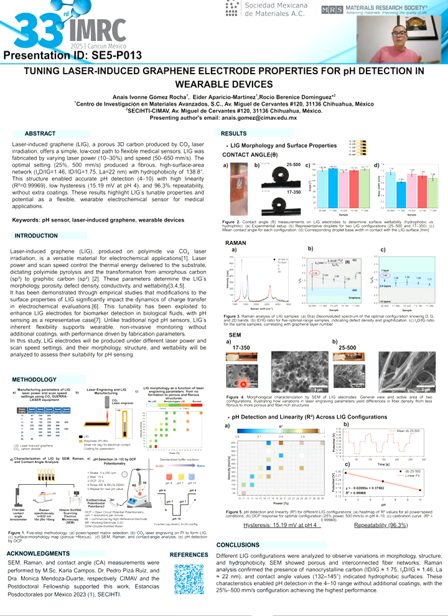In figure 4, SEM images are presented for two selected configurations, 17-350 and 25-500, to reveal differences in fiber density, only as an example to illustrate the morphology. The images reveal differences in fiber density and porosity depending on the laser parameters, from less fibrous surfaces to highly porous and fiber-rich networks. This morphology variation can directly affect the surface area and the charge transfer during the electrochemical sensing.